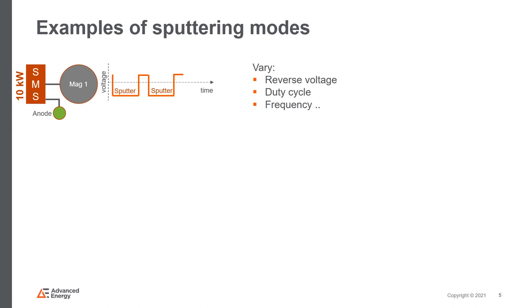As this is a vendor innovation showcase, I would like to highlight some of the work presently under research at the lab. Different modes of sputtering offer different advantages. For example, with SMS — single magnetron sputtering — where one target is powered with one power supply, one could apply either a straight DC deposition mode or a pulsed DC mode against an anode. Charge buildup at an electrode can lead to arcing in certain target materials, which is damaging to the growing film and the substrate. In this case, pulse mode of deposition may be helpful.